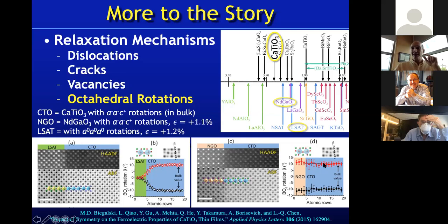The final state is actually quite similar. You'll see there are 10-degree rotations in both of them, but the substrate neodymium gallate started with huge rotations, and so those rotations evolved to that of calcium titanate, whereas here they started with zero and worked their way up to that of calcium titanate.